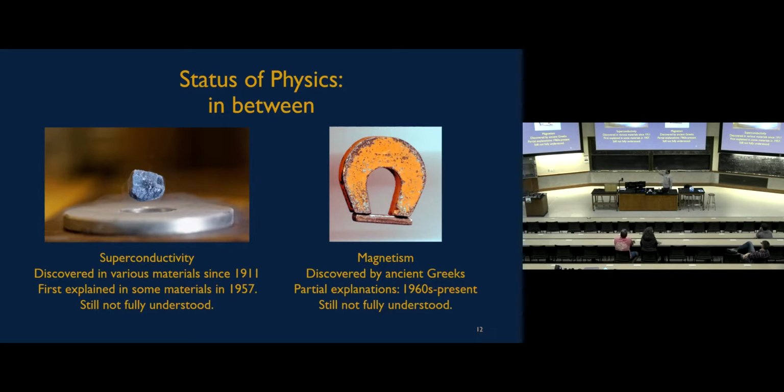So this superconductor is called YBCO, yttrium barium copper oxide. It's a complicated material, but the reason we use it is because you have these tanks of liquid nitrogen, and this material becomes a superconductor at liquid nitrogen temperatures. Now, many other materials can be superconductors, like aluminum or mercury, but you have to cool them down a lot more in order to make them superconducting. So when we give demos here in this room, for example, we only use high temperature superconductors.